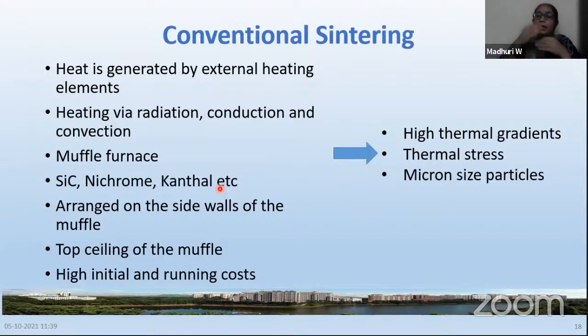So what does that mean? You have a temperature gradient, is it not? From center to the end of your material, there is a temperature gradient. There is a change in temperature with x or with your radius r, in a pellet or whatever this thing is. So there is a temperature gradient, and these temperature gradients lead to thermal stresses in the material and would affect the grain size and the microstructure of the particles or the ceramic. Fine. So these are a kind of disadvantages.